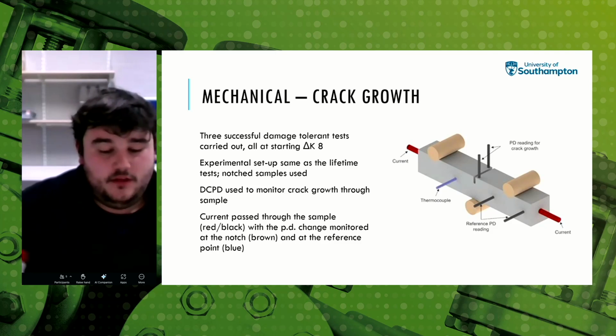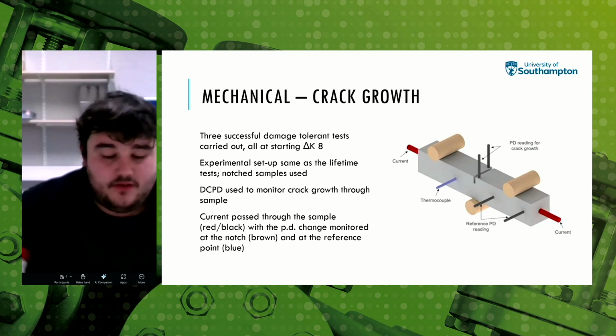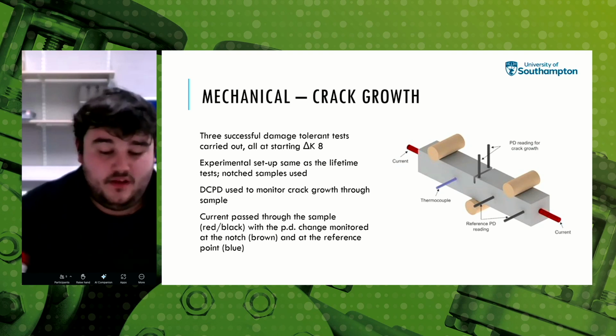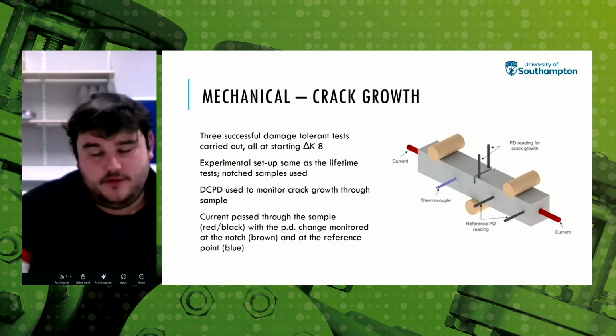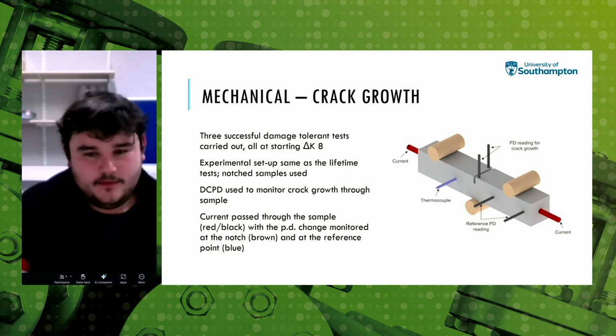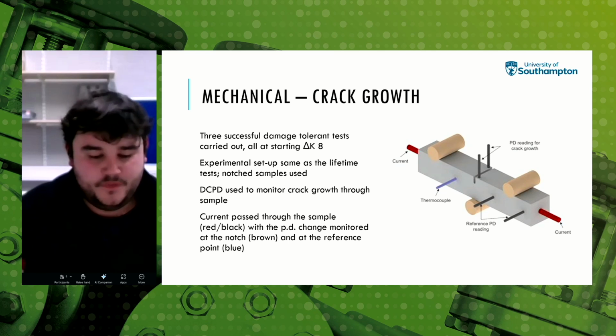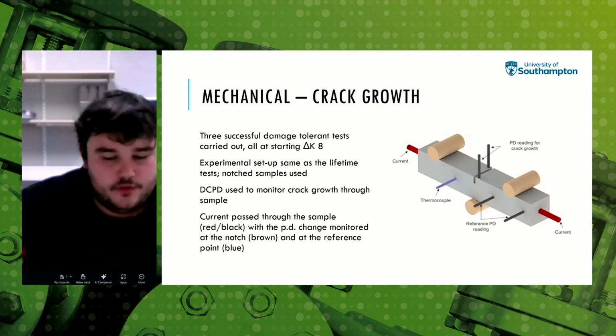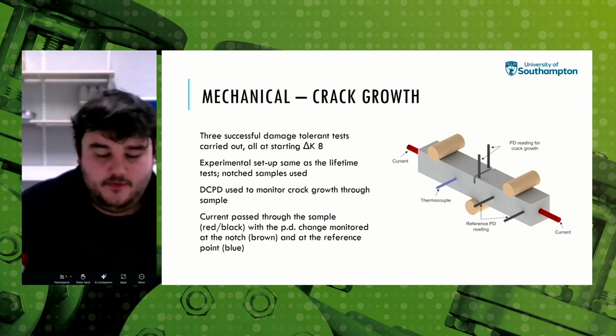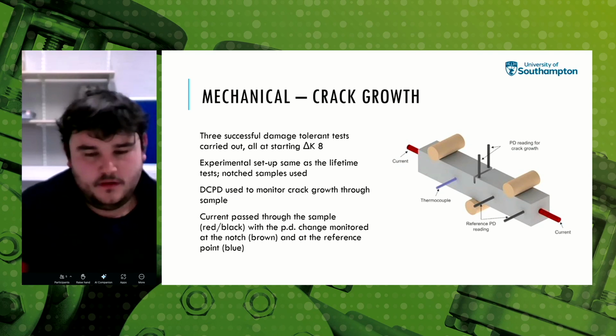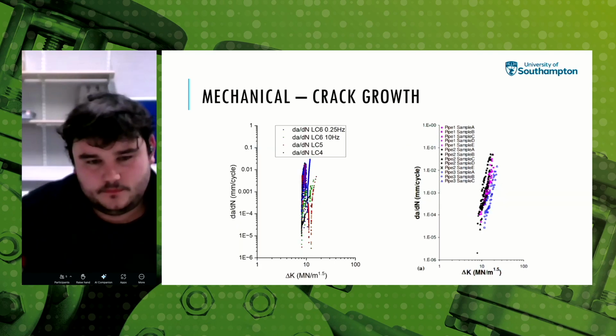So if we look at the crack growth in damaged pipelines, we have pits on this surface that will then soon initiate cracks. We've done a number of damage-tolerant fatigue tests. We take a bend bar sample and we insert a sharp notch into the sample to induce a stress concentration to facilitate a crack in the centre where we can monitor it. We monitor the crack growth rate through the sample to understand the failure mechanisms when a crack is already initiated. Go to the next slide, please.